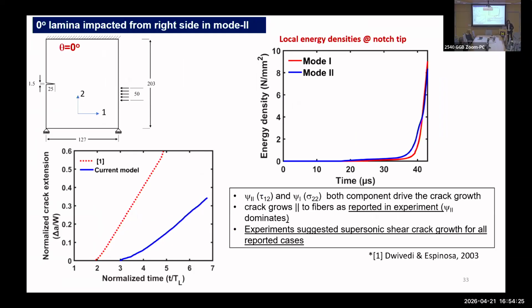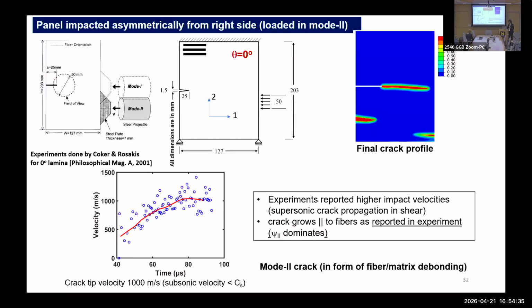And we have identified the reasons for not getting the quantitative prediction to match. One of them is, of course, that in the experiments, they have not reported multiple cracking. We are observing more than one single crack propagation. And remember, every crack demands some energy. So whatever we are tracking is getting distributed among these 3 branches in this case, but they have seen only one major crack propagation. We did not try to constrain the damage anywhere in the domain, so that lets the simulation do whatever it does and see where we stand in terms of prediction.